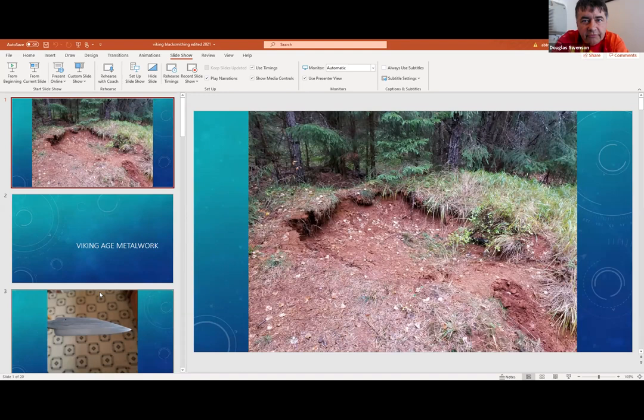They would fire this furnace maybe 5 to 6 hours, and then eventually they would end up with what we call a bloom. Let's hold that up. An iron bloom, which is, hard to say, maybe 70 to even 80% iron at this point, but it has a lot of impurities in it. It comes out of the furnace at a welding heat, a dazzling white color, over 2000 degrees, and we would start to refine it. We would start to hammer it very gently, usually with wooden mallets.